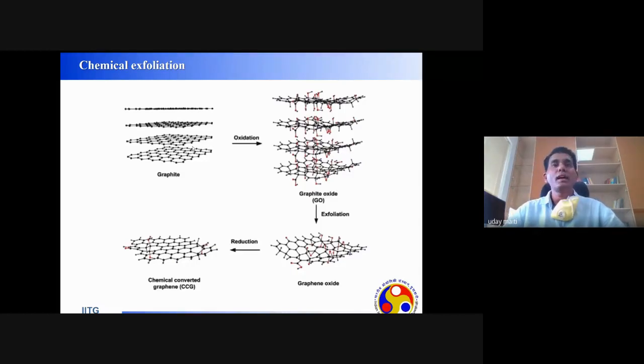They took natural graphite and wanted to reduce the van der Waals interaction between the graphene sheets. So how to reduce the van der Waals interaction? Because van der Waals interaction depends on the distance. If you can increase the distance, the van der Waals interaction becomes very small. So what they did was make some chemical treatment and attach some functional groups over the graphene planes. As a result, the distance between the graphene sheets increases a lot, and there is very little van der Waals interaction. Even if someone does some handshaking, they can separate individual layers.